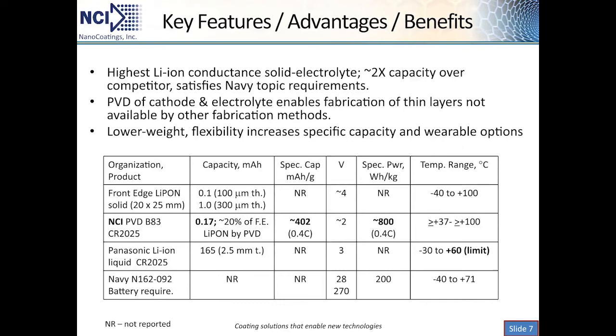The table below shows some of the data that's been obtained in the open literature. In the second row is one of our cells from PVD B83, a CR 2025 cell. We can see that our capacity is approaching 2 times the capacity for the leading front edge LiPon cells, and this is with a much thinner layer. We're talking about one mil or so, 1,000th of an inch. The specific capacity, as I stated earlier, is 400 milliamp-hour per gram. That's under charge conditions. Under discharge, we're at about 115, so we have a little bit of work to do in that range. But by increasing the amount of the active cathode material, we should be able to get there.